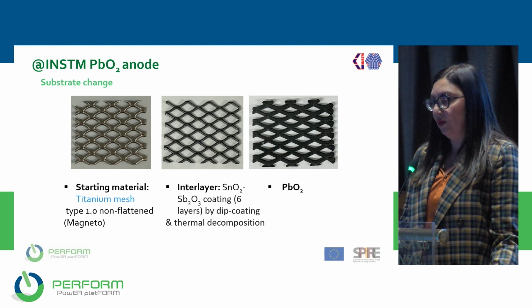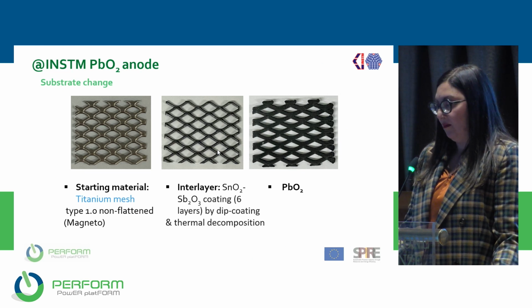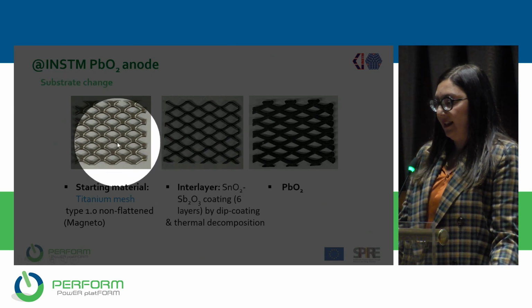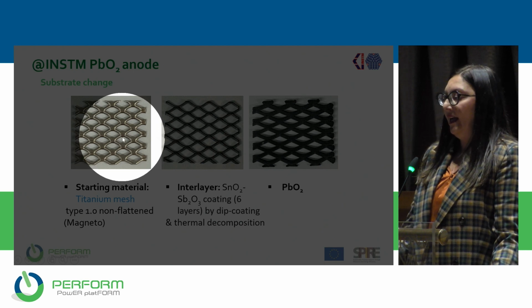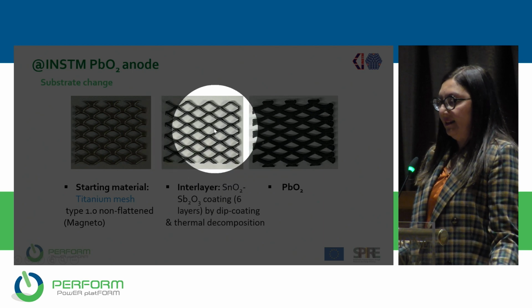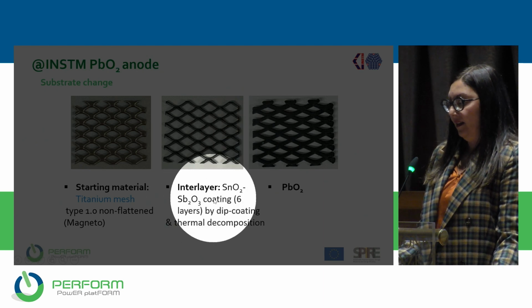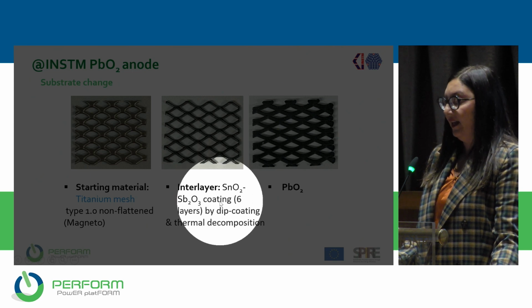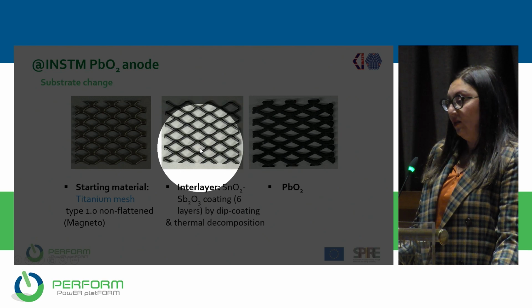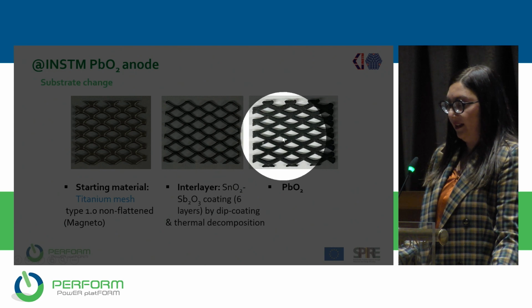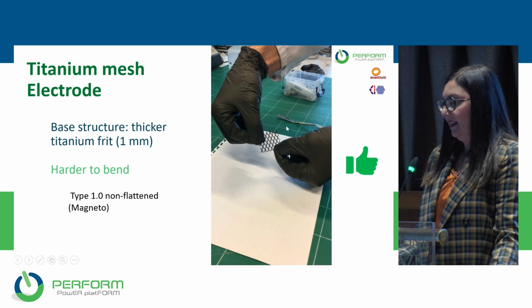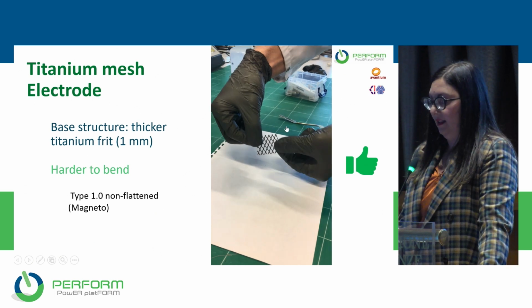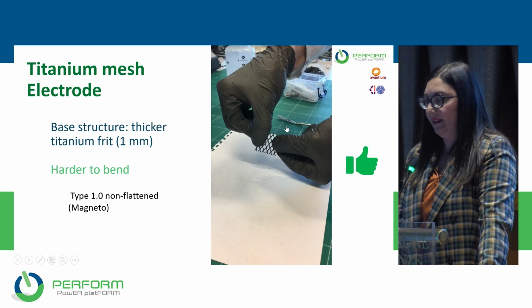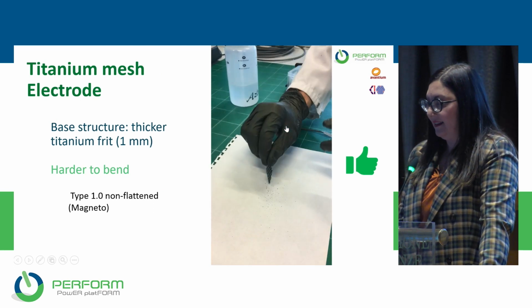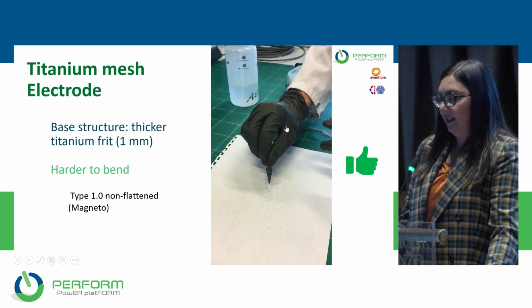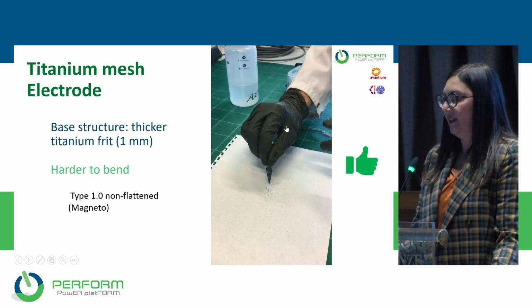After, we decided to modify the structure of the electrode, changing the substrate, and we used a titanium mesh like this that was covered by an interlayer. This interlayer was made with a tin dioxide antimony trioxide coating that ensures good adhesion of the lead dioxide that was electrochemically deposited, as I showed you before. And this new electrode was a good electrode as far as mechanical stability is concerned, and the requirements are good for the preparation of the system for the upscaling.